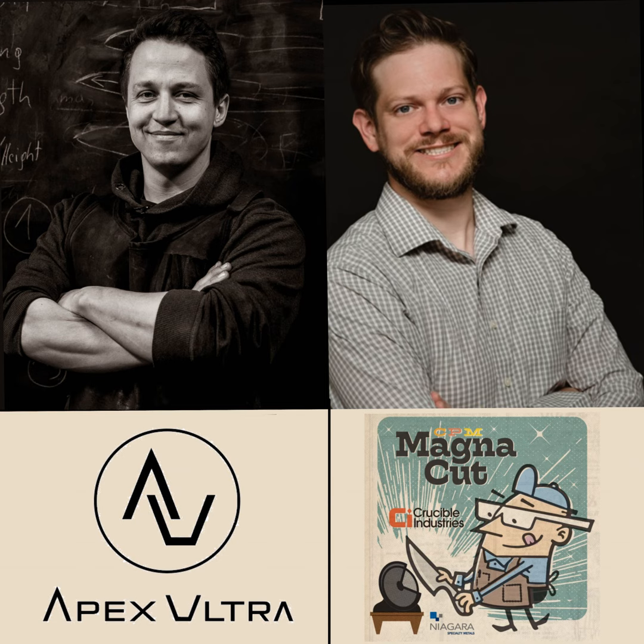In general, yes, if you can. It's not strictly necessary. It makes a fantastic blade without cryo treatment. But if you have an option to cool or deep freeze or cryo, then use it. Especially in the bladesmithing classes, I only use the freezer and not the cryo treatment with liquid nitrogen, simply because liquid nitrogen always has a certain risk of cracking blades. Even just a layer of decarburization can be enough to rip your knife apart. So if you're making a class, you want to go home with a knife, and I don't want to have split blades. We might lose a few percent of performance if you don't use cold treatment, but in general, we get fantastic results with just using a freezer.